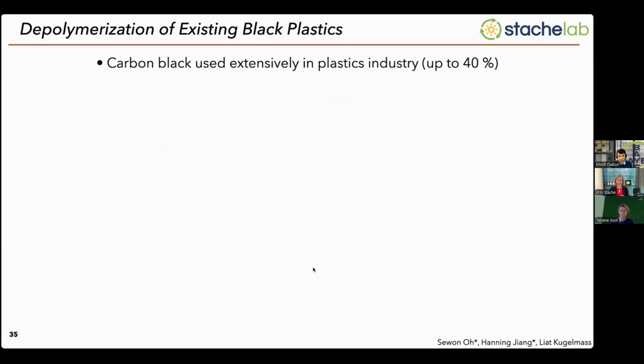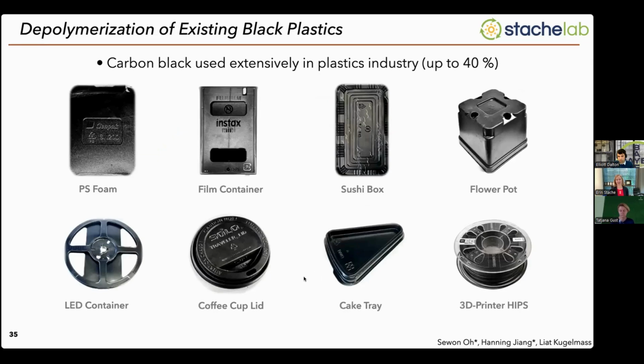And then, of course, does this work on existing commercial waste? Like I said, carbon black is used extensively in the plastics industry, up to 40 weight%. These were just 8 different polystyrene containing samples that we collected. We know they're polystyrene because you can see here, there's this little number 6 polystyrene resin identification code. All that tells us is that it has polystyrene resin. It doesn't tell us how much. It doesn't tell us the carbon black loading. It doesn't tell us what plasticizers or surfactants or other inorganic additives or other copolymers might be in there. But we know that it has polystyrene resin.